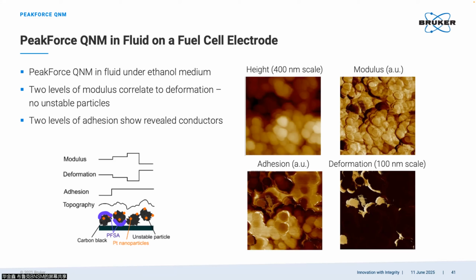it shows the highest modulus. And we also observed some no-modulus particles. These no-modulus particles, we think, are unstable particles. They are just squeezed up by the other particles. And if we use AFM probes to compress on it, we just squeeze it back in. So the modulus shows, okay, it is kind of a soft one. So it's quite interesting results.